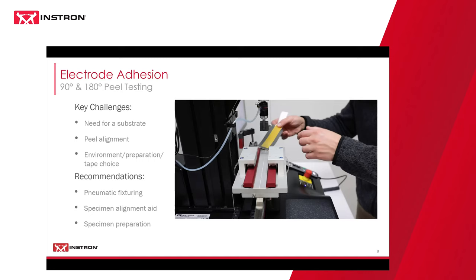However, that brings us to the next thing, peel alignment. While 90-degree peel does not need a substrate for the majority of the testing, 180-degree peel testing does have an advantage because it is what we would consider self-aligning. As long as you set up the 180-degree peel test with a substrate and at the right angle properly, it'll pretty much self-align to 180 degrees as you begin your test. For 90-degree peel testing, on the other hand, most fixtures are designed to have a one-to-one ratio of sled movement to crosshead movement. So if you set it up at, for instance, an 85-degree angle, it's going to maintain that 85-degree angle throughout the test. You're not going to reach 90 degrees. And that alone can add variability in your results, especially if your operators aren't able to properly ensure alignment each time.